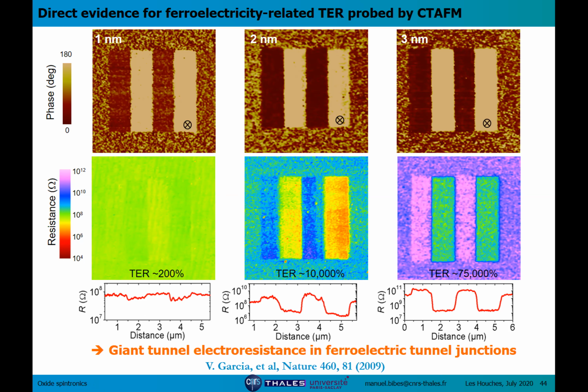And you can compare this with the best values of TMR at room temperature. Even with these MgO barriers, it's never more than 1000%. So this is a very, very large effect.